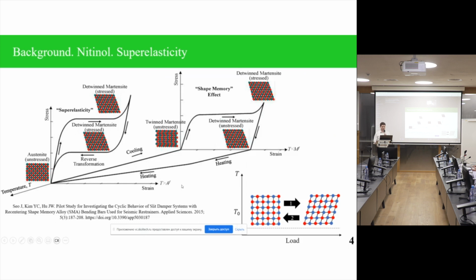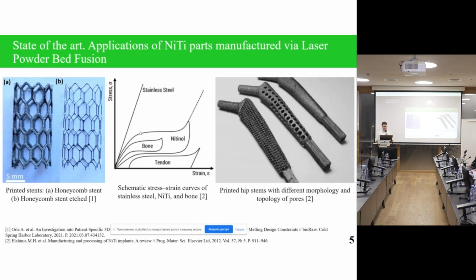But also on this slide, we can see the fundamental dependence of the mechanical response of the shape memory alloy on the transformation temperature. So if we load our material at ambient temperature below martensite finish, we observe the shape memory effect. If we load the material above austenite finish, we have superelasticity. So both effects are used in many industrial applications, and some of these applications can be more efficiently manufactured by 3D printing.